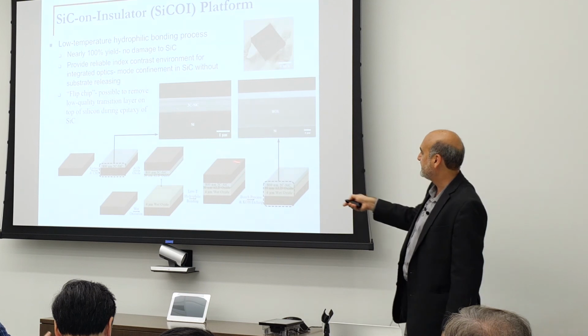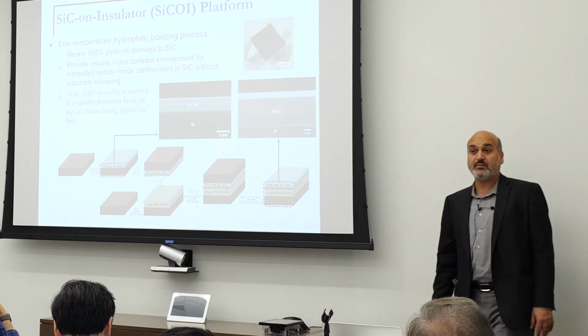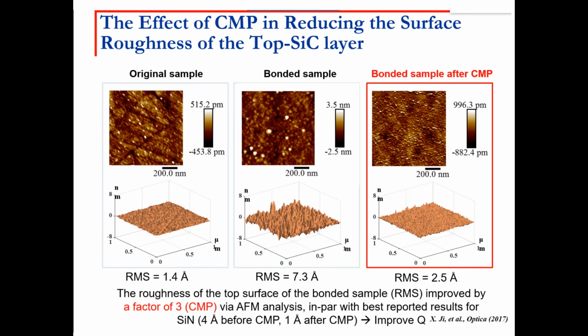I access this side, and then we do chemical mechanical polishing on that in order to bring the quality up. So that's the original sample. As you can see, the top layer of the original sample is very good. That's where we bond and bring the bottom layer up. That's very terrible. These are AFM images that show the surface roughness. And then after chemical mechanical polishing, we get much better performance.